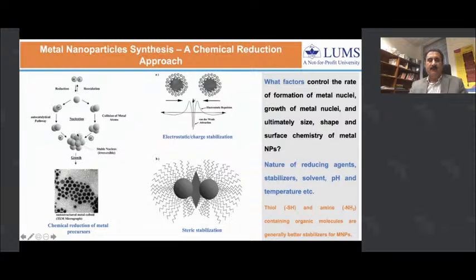We control the size basically by adding a stabilizer -- for example, if thiol-based or if they have amine groups -- which can coat these nuclei at a very early stage and stop the growth of the nanoparticles into bigger particles. In this way we can tune the size, shape, and finally the surface chemistry of these nanoparticles. Once these particles are formed, they are still very small, smaller than 100 nanometers, so they have huge surface energy and tend to agglomerate -- so we really need to stabilize them.